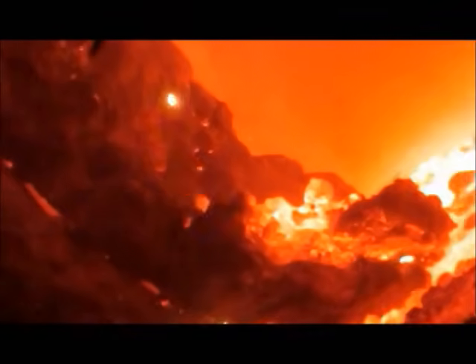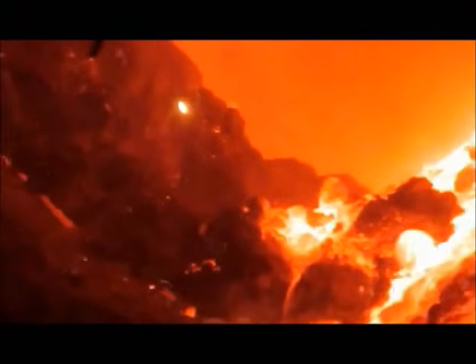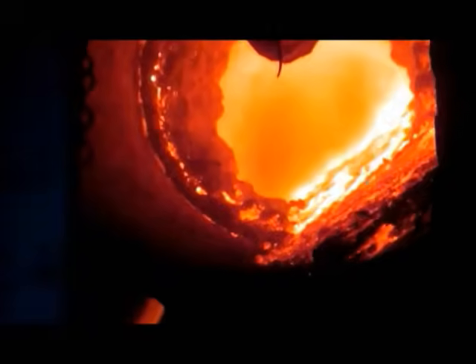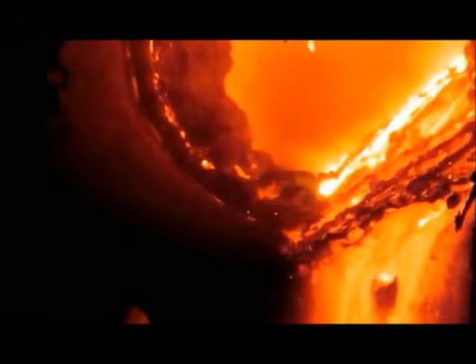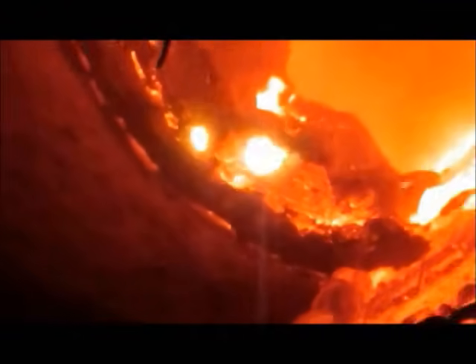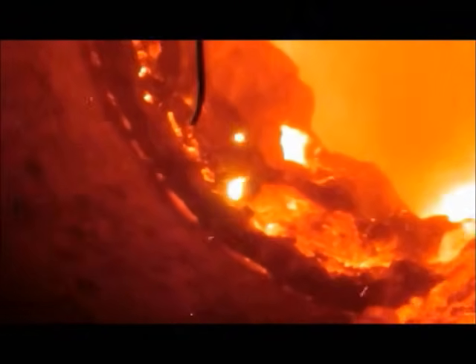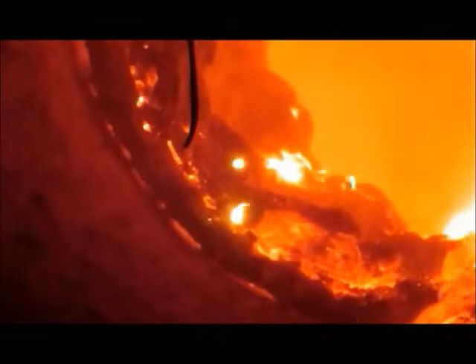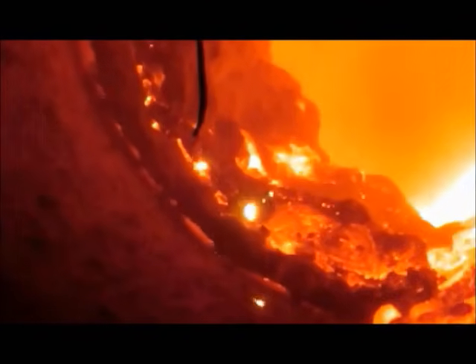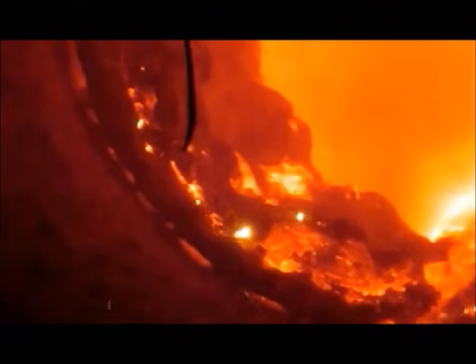Under unique circumstances, during specific production, it is possible to remove the ring when it is almost as long as the kiln itself. With big rings, you can use the gun to shave rings down in size by shooting continuously, parallel to the kiln side, while the kiln rotates. This method will keep the kiln in operation. But consumption of cartridges can be enormous, and may reach up to 3,000 per day.